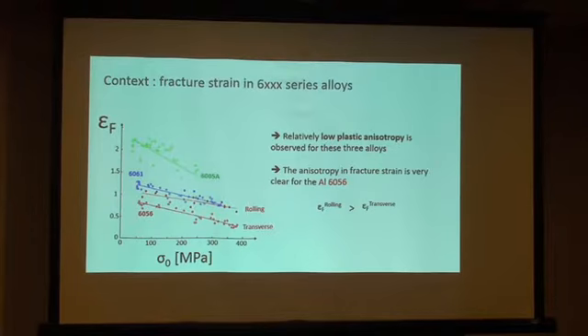Also, another observation that we made is that for the aluminium 6056, there is a strong anisotropy of the fracture strain. However, if you look at the plastic anisotropy, if you pull in the transverse and the rolling direction, the tensile curves will be quite similar. But you see that the fracture strain is highly different. So this means that there must also be an effect of the microstructure on the fracture strain within this material.